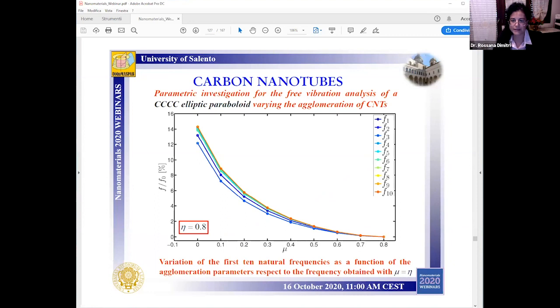Here we repeat the systematic analysis for a fixed value of eta equal to 0.8, while increasing gradually mu up to the same value of eta. So note the monotonic decrease in behavior for each vibration frequency, which corresponds to a reduction of the structural stiffness because of the agglomeration effect of carbon nanotubes within the matrix.